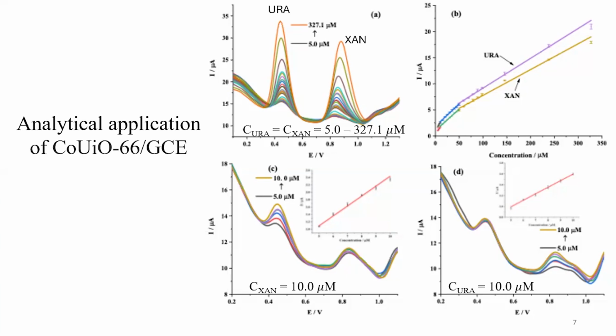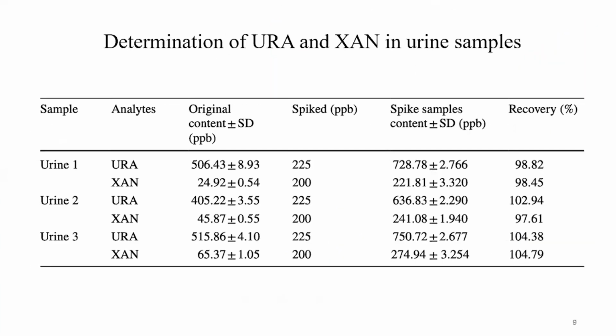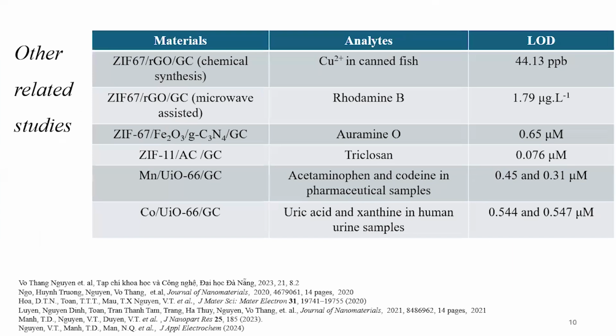We also used this electrode to do quantification in real urine samples. We had three urine samples with a spiking technique, and we obtained acceptable recovery. This is the other related study where we use MOF-based materials to modify the electrode and use those electrodes to detect other kinds of analytes, from metal ions in the solution to organic analytes in the solution. We do both simultaneous detection of two analytes and detection of single analytes.